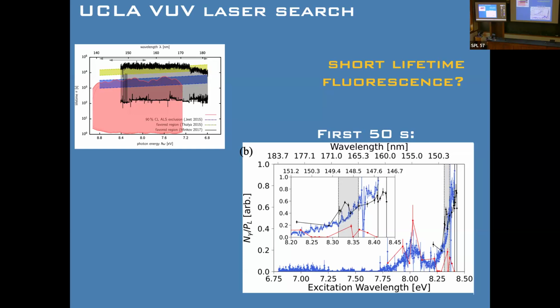Now at this time, there were other measurements in the field, indirect measurements, mostly from Peter Thirolf's group in Munich, where they were looking at an electron-enabled quench of the nucleus, and started to say the transition was probably somewhere around 8.4, 8.5 eV. Still a big range, but it was in this region. So we started to think maybe this is the nuclear transition, but our original understanding of the crystal was just incorrect, that it's affecting it more than I showed you in the first slide.